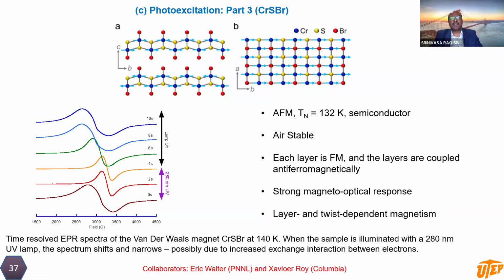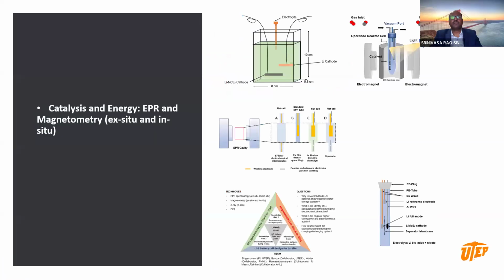So we extracted all that information as a function of temperature, time, and angle, and we are putting it together to see what exactly is happening between the light we shine and the local optical phonon we generate in this material. That could tell us that there is something happening at the chromium site by interacting with applied photons.